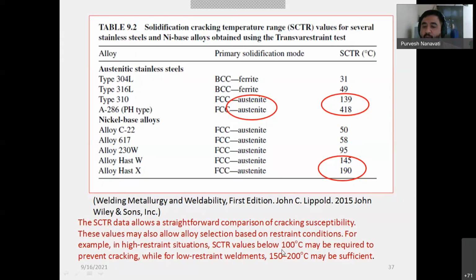Here the note is also written: SCTR value below 100 degrees Celsius may be required to prevent cracking, while for low restraint weldment 150 to 200 degrees Celsius may be sufficient. For low restraint, you can go for this, but for high restraint, it is not recommended. Okay.